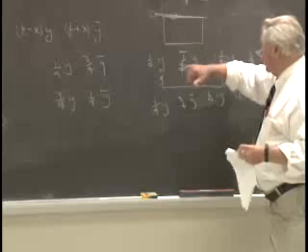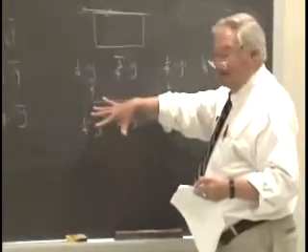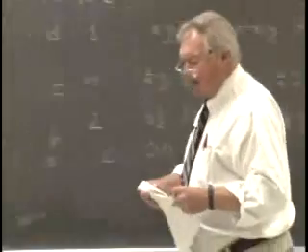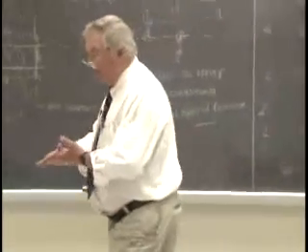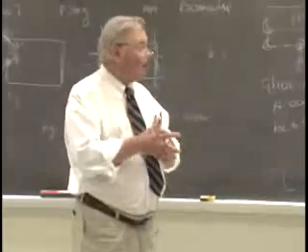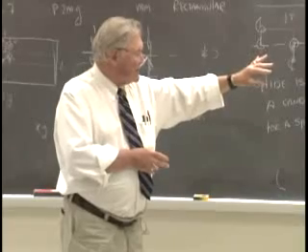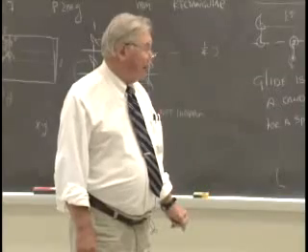Okay, so what this is telling me analytically, if I just plug in the coordinates of what seems to be a distinct special position, is I get the same atom on top of itself twice. And it looks exactly like choosing the first mirror plane. So that's a good way of checking, particularly in a very high symmetry where there are all sorts of sites of possible point groups that could cause coalescence, to just crank out the coordinates and see if, in fact, you've got exactly the same pair with the same coordinates that correspond exactly to the x and y of some previous location that you identified.